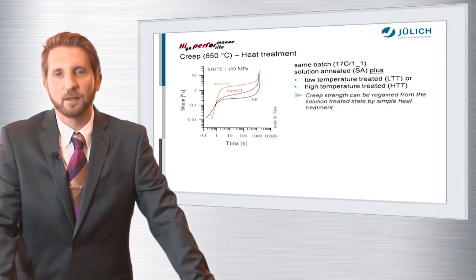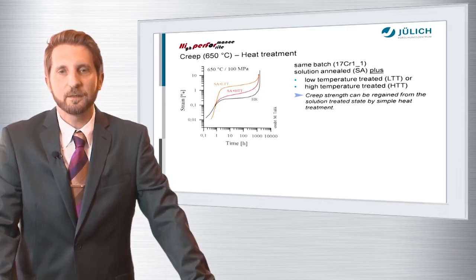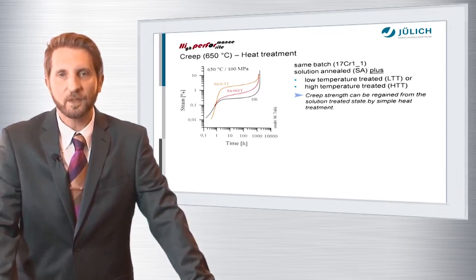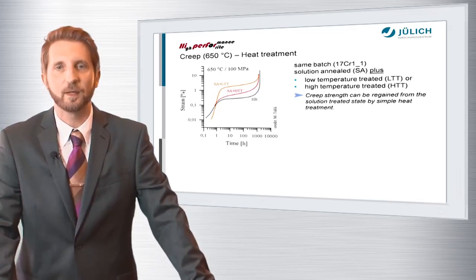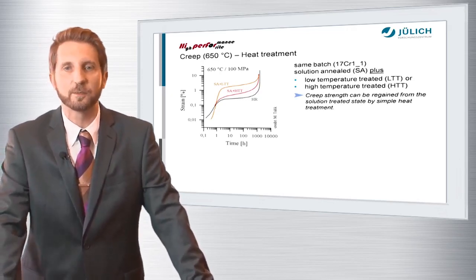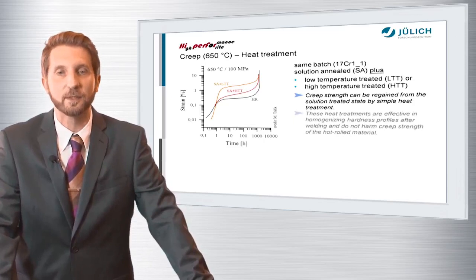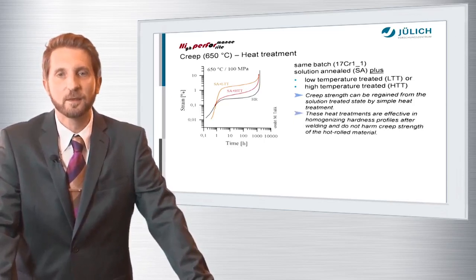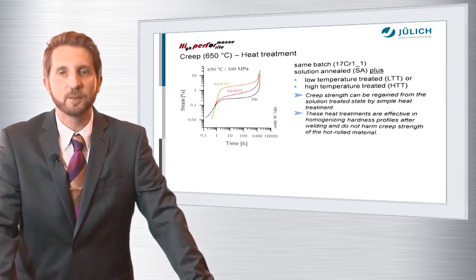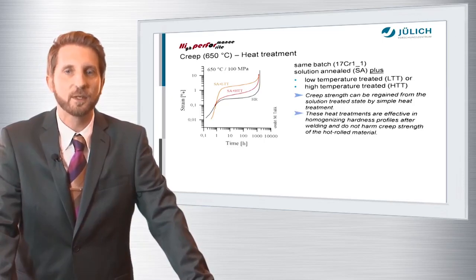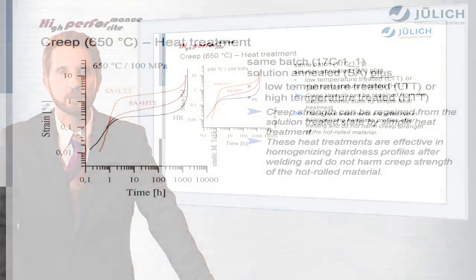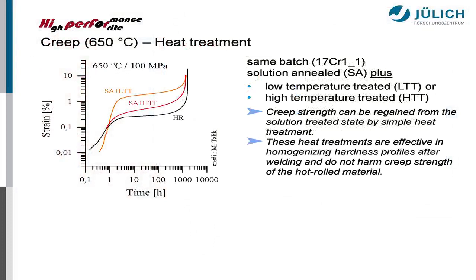And you can see that both of these solution annealed and heat treated materials approximately reach the same creep rupture strength as the hot rolled material, and that means that creep strength can be regained from the solution treated state by simple heat treatment, and this is very beneficial. Furthermore, these heat treatments are very effective in homogenizing the hardness profiles after welding, and they do not harm the creep strength of the hot rolled material.